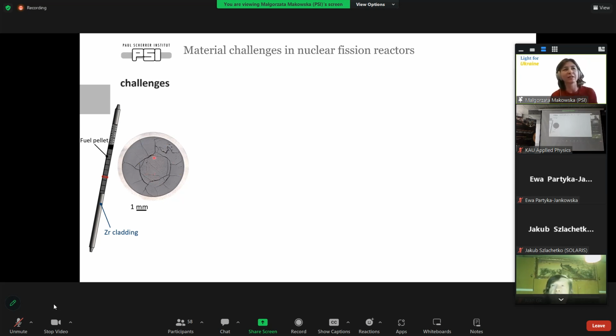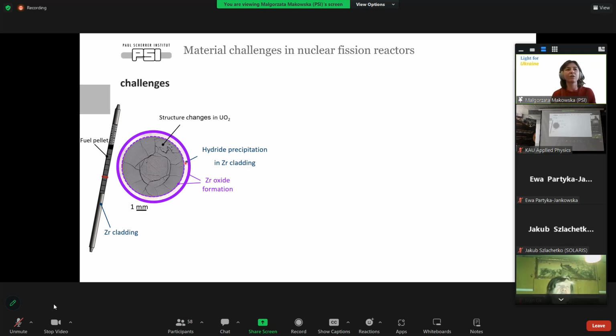This image shows a pellet of spent nuclear fuel. This is essentially uranium oxide placed in a cladding made of zircaloy. During the operation of the reactor, we observe a number of structural changes inside the pellet, inside the uranium oxide, but also precipitation of hydrides in the zircaloy claddings. We have oxide formation on both sides of the cladding, and all these phenomena. Then we can also have some deposition from the cooling water on the cladding, and all these phenomena can potentially lead to some failures. I mean, we prevent them, but they can lead to failures that we need to understand well.